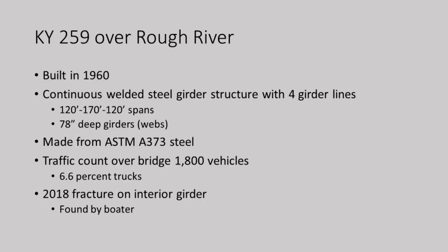And then the light goes on, and we figure out, well, that fatigue was low cycle fatigue. When you get low cycle fatigue, a lot of times it just looks like a tensile test. You can't see striations or beach marks or anything, and that's basically what we were seeing. We think that the fatigue was due to these periodic heavy farm to grain elevator loads, and we think because of the distortion in the web that we saw, that the girder was very heavily loaded at the time of fracture. So it may have had a heavy truck on one side of the pier and a heavy truck on the other, or maybe 4 of them. It was the straw that broke the camel's back, proverbially. So now let's go look at our last case here.